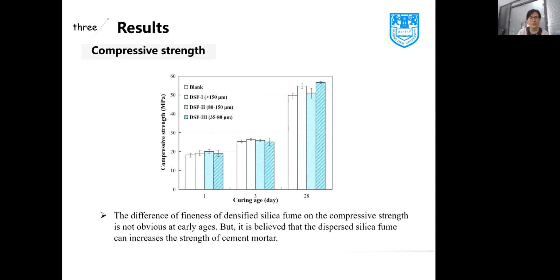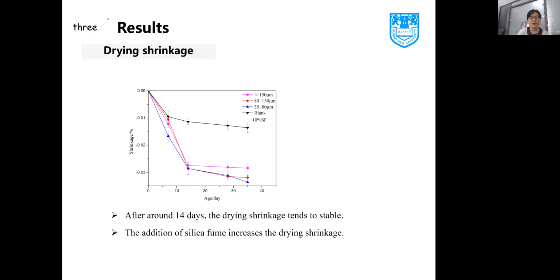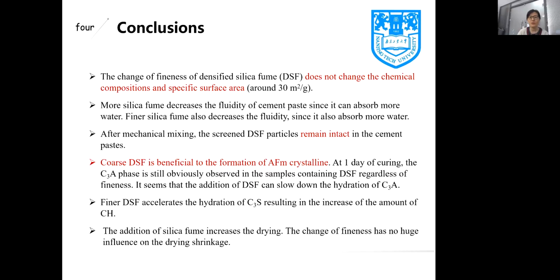This is the compressive strength of cement mortar. The difference of fineness of silica fume on compressive strength is not obvious at early age, but we believed, also from the literature review, that dispersed silica fume or silica fume treated by ultrasonic can increase the strength of cement mortar. Here is the drying shrinkage of cement paste. We can see after around 14 days, the drying shrinkage turns to stable, but the addition of silica fume increases the drying shrinkage. Here we go to the conclusion.